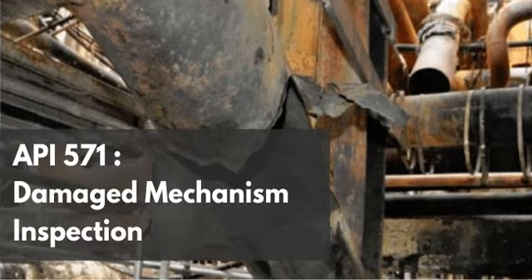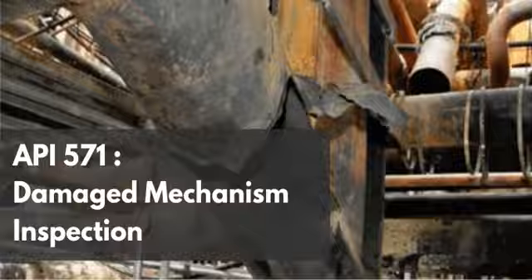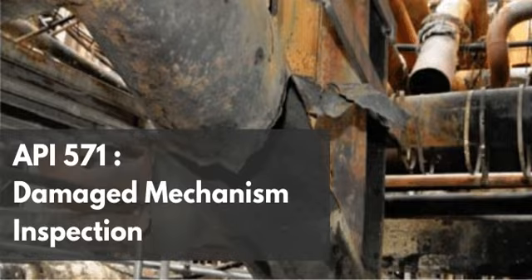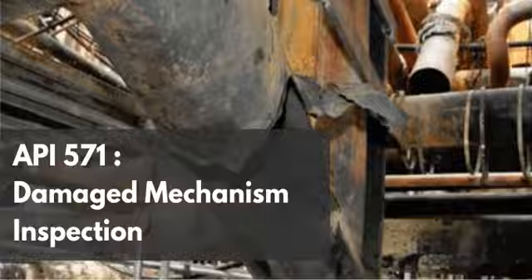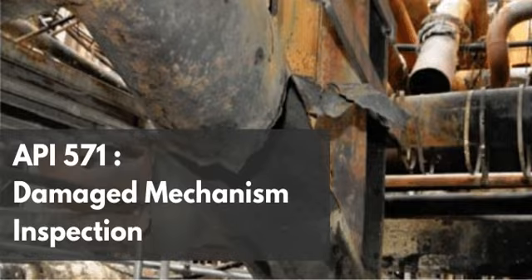So you might have a downstream fuel gas piping circuit or a section of the hydroprocessing unit made of standard non-PWHT'd carbon steel. Right, because the design engineers never intended for that pipe to see amine, so they didn't mandate the expensive heat treatment during fabrication. But suddenly, due to an upstream foaming upset, hot amine is introduced into that piping. And boom, the stressed welds in that downstream system are now exposed to the exact environment required to initiate Amine SCC. It really forces inspectors to track the actual flow of process upsets, not just the intended flow lines on a piping and instrumentation diagram. You have to think outside the normal operating window.